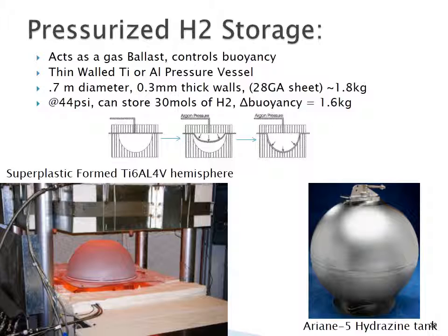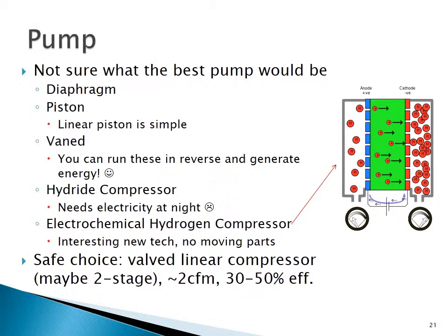If you did it in Kevlar or Spectra, you could have a very lightweight tank. Composite tanks are tough to do because you cut through them and you induce stress risers around the holes. Metals are a little easier. It's just very thin walls are tough to manufacture in metals unless you do some interesting techniques. Superplastic forming is one of those techniques that you might look into, because you can superplastic form titanium and you can superplastic form aluminum lithium, both of which are very good lightweight materials to use for this.